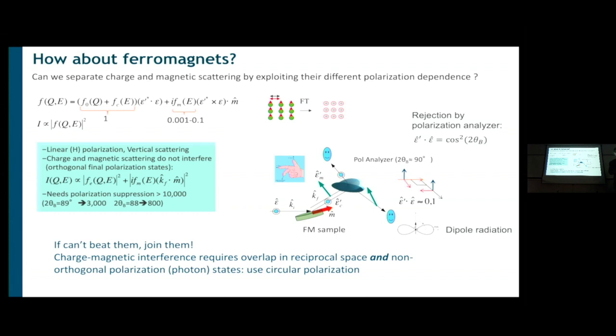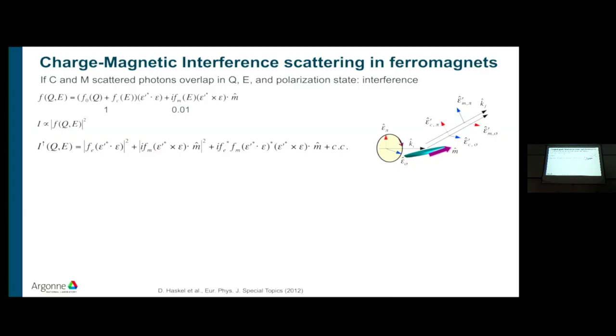They have the same energy. They show up in the same Q vector, the same point in reciprocal space, but they have different polarization here, so they don't interfere. One is horizontal, one is vertical. But if you use circular polarization, I will show you that there will be interference between the charge and the magnetic scattering, and we can leverage that for our advantage. And let me show you how that works.